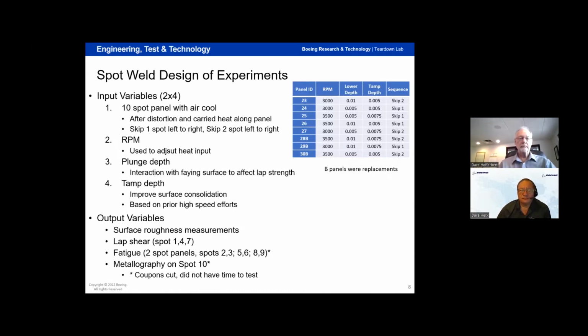And looking at our output variables, looking at the surface roughness, because this does have to go through the air and have a nice smooth surface on the outside. The lap shear, as we're comparing to a rivet, which is the same for the fatigue. And then also doing a metallographic cut just to make sure you're getting a good consistent structure throughout the spot weld.